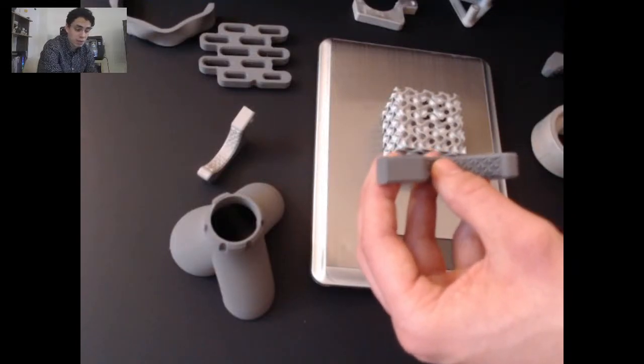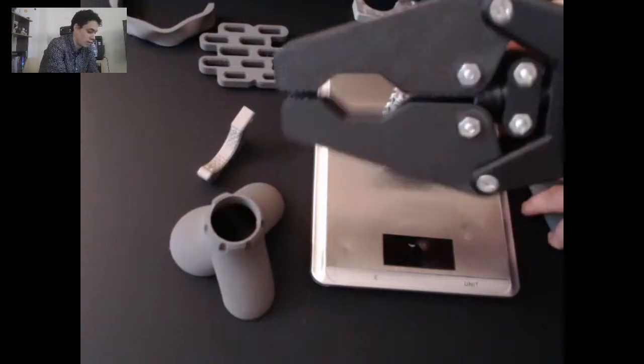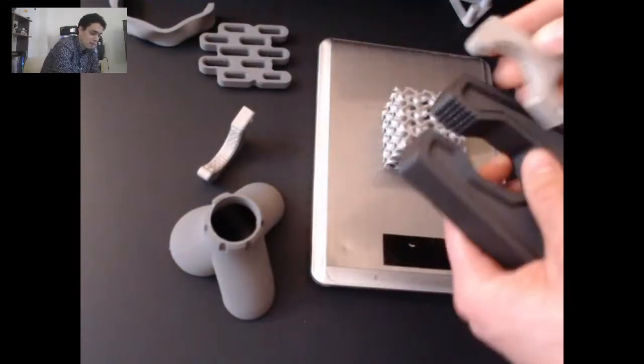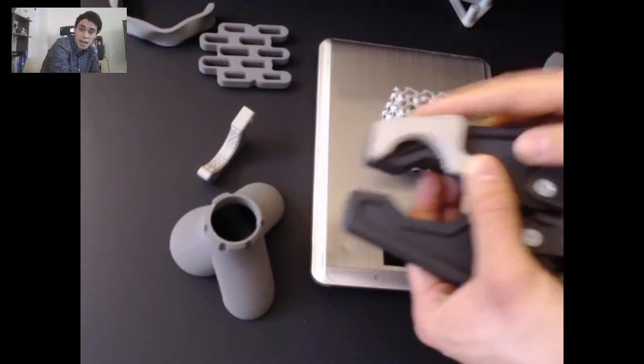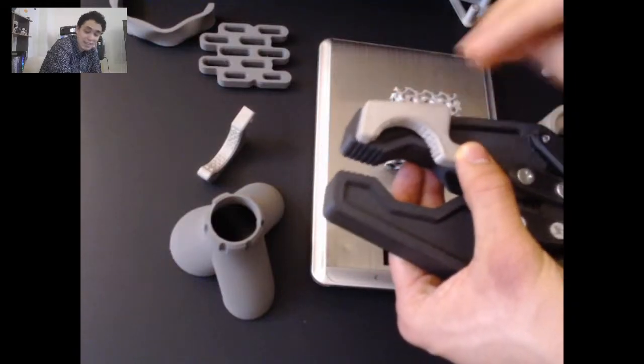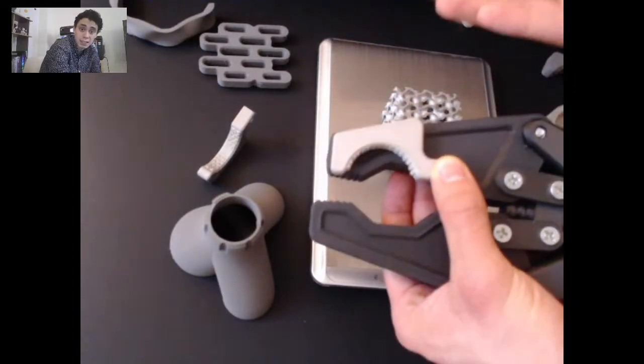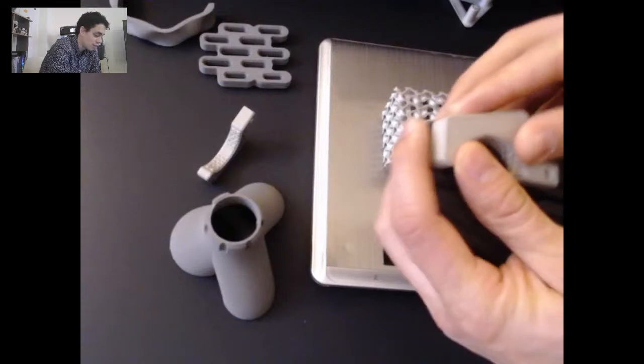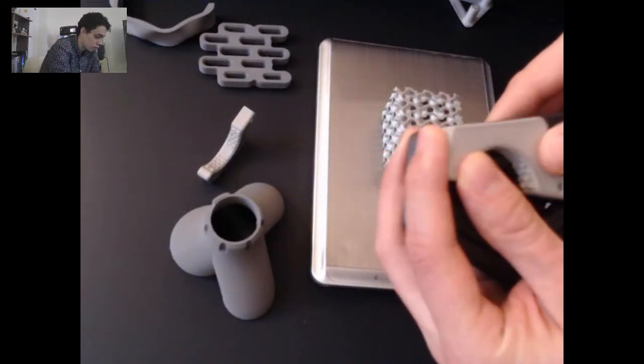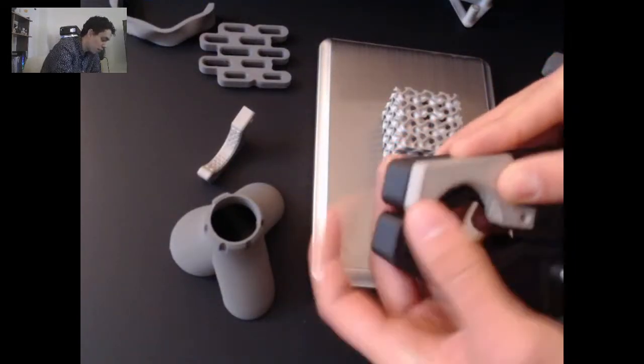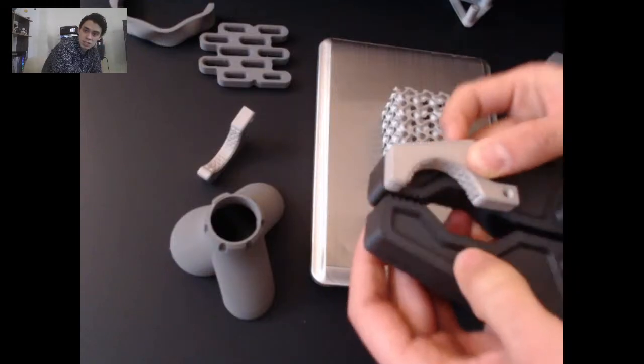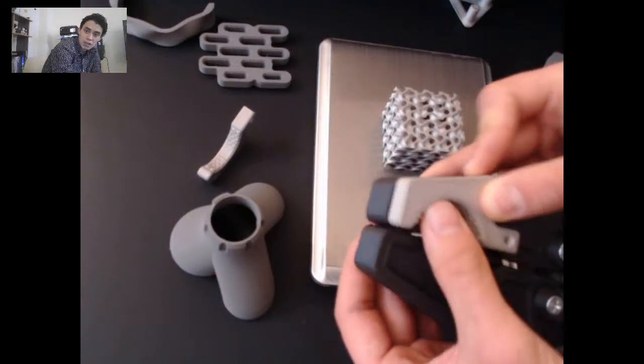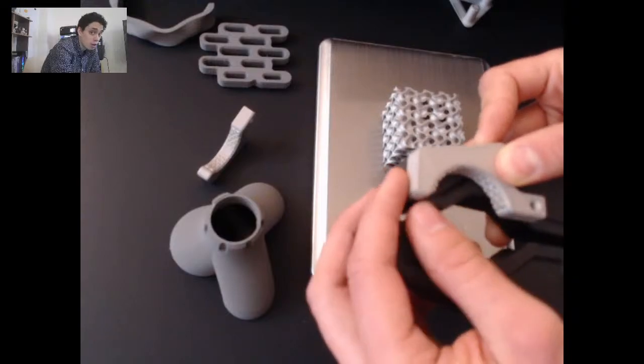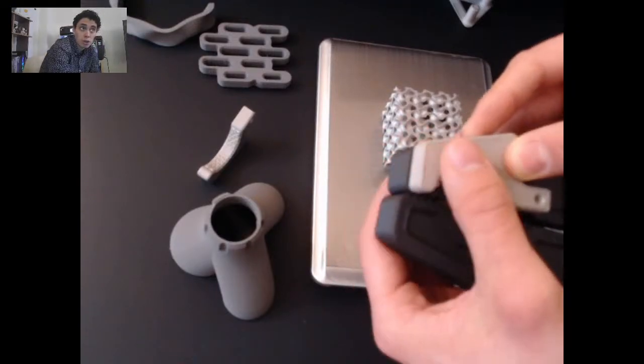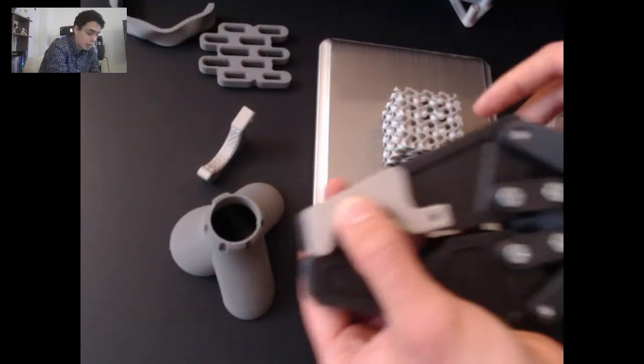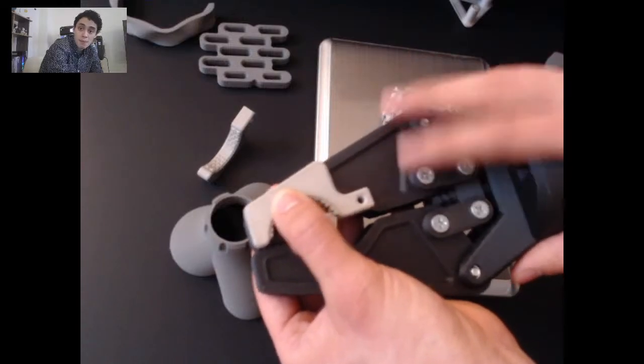One thing that I would recommend, and I think this is a good example too, right? I have my gripper here. These front claws are the exact same geometry from the gripper, sent out for sintering. As you can see, the geometry is fairly close. Even with MakerBot Print, we accounted for that shrinkage, and the part is really, really close to the actual spec part. It's not 100% there. It's not as close a tolerance as you would get with ABS, or with carbon fiber, for that matter.